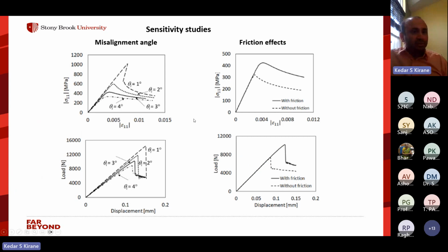Then we did some other studies, sensitivity studies, and essentially we can see that it can capture the effect of misalignment angle. So higher misalignment angles, lower strength. And we also were able to quantify using the model how much effect the friction has on the overall behavior. And we can see that it is actually quite significant. If you run the model without any friction effects, the peak load decreases, the load after the kink band also decreases a lot. So the friction in the crack faces plays a very important role in compressive failures, and that also needs to be included in the models.